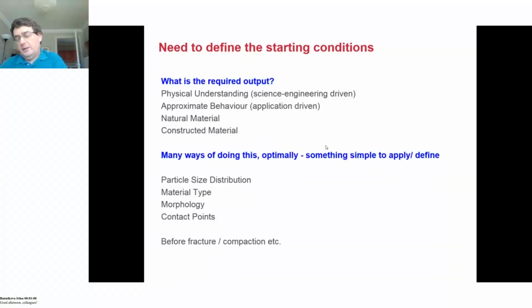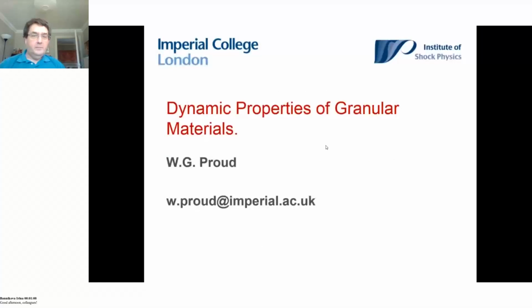Now, Oleg mentioned in the first tutorial the Swegle-Grady relationship, where strain rate to the power 4 is linked to stress. For granular materials, that power law is about 2.5. So strain rate to the 2.5 is proportional to the stress in the system. So that's a key thing. So that is the end of this particular presentation, and thank you.